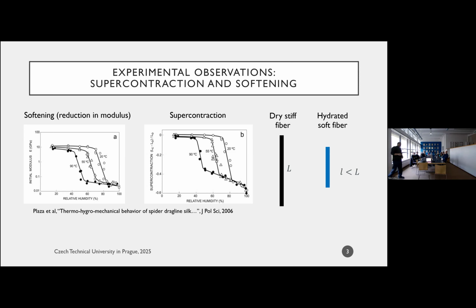So what you can see here is that as long as the ambient environment has a relative humidity of less than 75%, nothing really happens. The stiffness of the fiber is about 10 gigapascals, and the supercontraction strain is, for all intents and purposes, 0. Once I pass the 75% mark, all of a sudden the fiber begins to contract. And it doesn't contract by a little bit, it contracts by a lot. We see that it contracts by about 60%. And if you look at its stiffness, we can see that it softens from 10 gigapascals down to tens of megapascals, right? So it's a very drastic reduction in stiffness. Okay, so that's the response, that's the supercontraction and the softening.